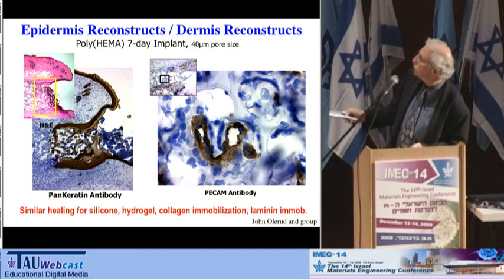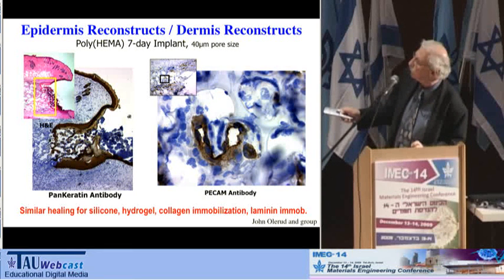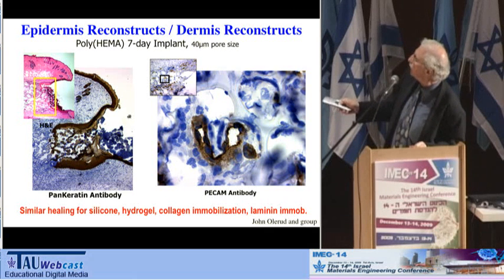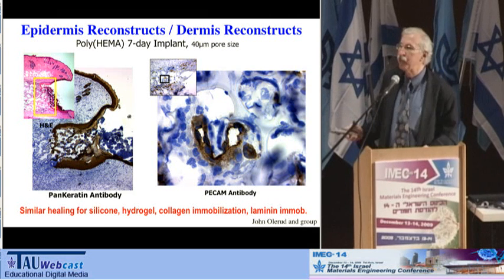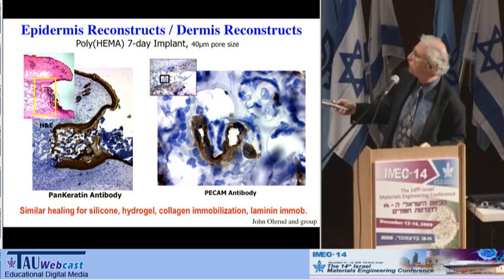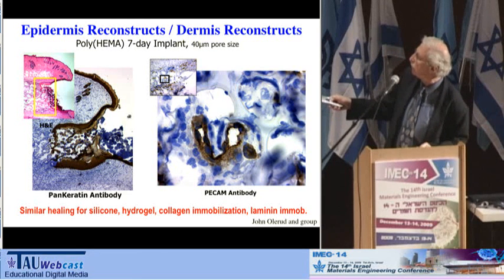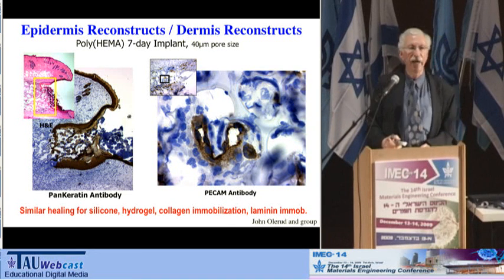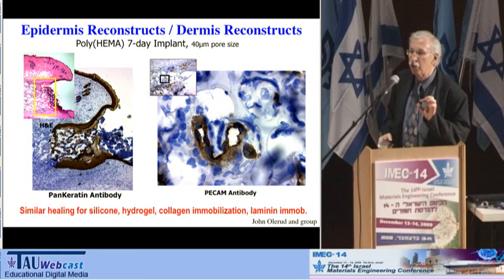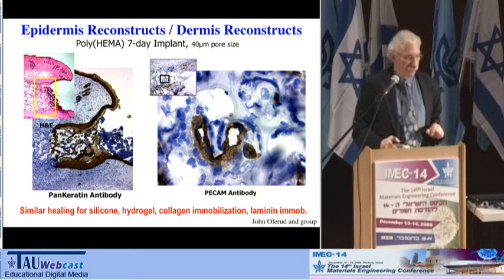And interestingly, this healing response was seen with a silicone elastomer, with a hydrogel. We immobilized collagen and laminin into these. It made no difference. We got the exact same healing response with silicone, hydrogel, with or without collagen or laminin. So it was controlled by the pore size, not the nature of the material.